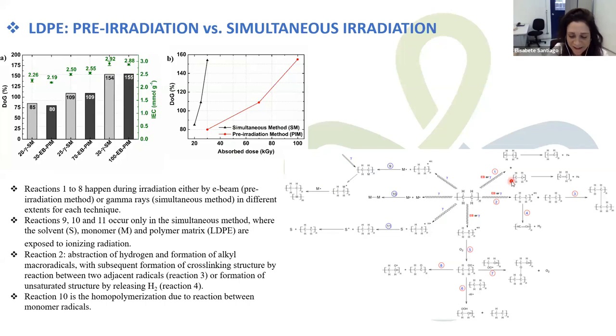An open question in the area was: does it make a difference producing AEM by simultaneous or pre-irradiation? So we have studied the AEM based on LDPE, low density polyethylene, prepared by both methods. For this comparative work, the dose rates were adjusted to obtain similar grafting degree and IEC values. As expected, in the simultaneous method, the dose rates are lower than the doses applied in the electron beam pre-irradiation method. In terms of radiation, several radical and chemical reactions are involved.